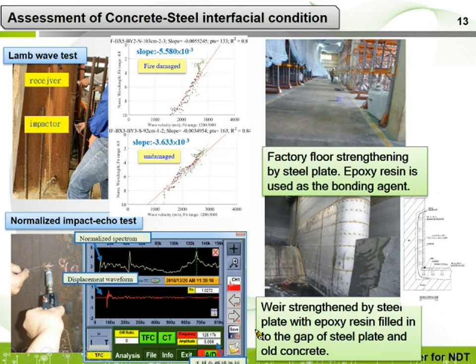One method is to place the small hammer impactor away from the receiver to obtain the Lamb wave modal vibration, and use the difference of the A0 mode dispersion curve of the steel plate to assess the debonding. The second one is to place the hammer close to the receiver and use the amplitude of the peak in the normalized amplitude spectrum to examine the voids underneath the steel plate.